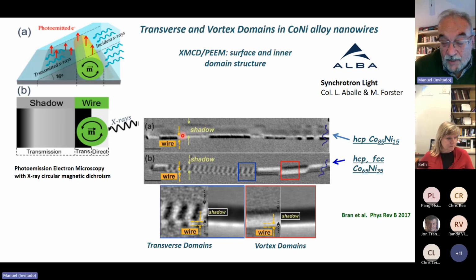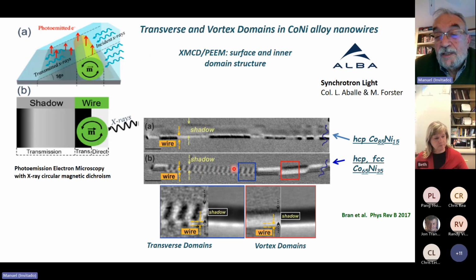So if we go back to the image obtained by PEEM with the circular dichroism analysis, we see some region with multi-domain structure here with the transverse domains. But here to the right, we have completely different contrast. We have here two vortex domains with different chirality, according to the interpretation of these images. So it is very important that we can have different domain structure depending on the crystal symmetry.